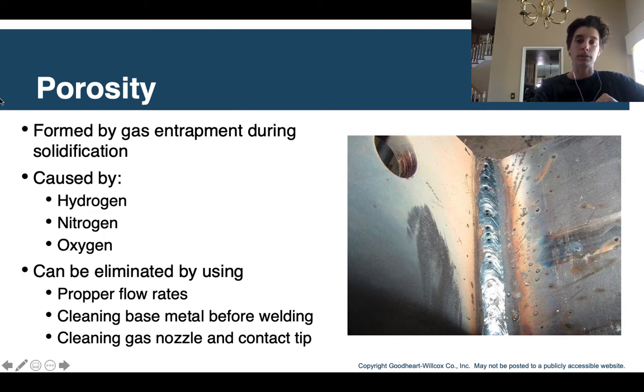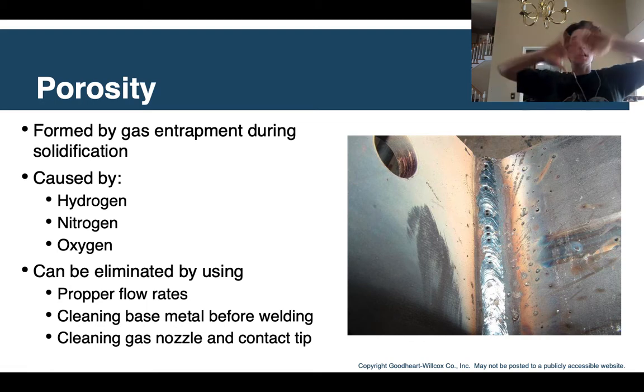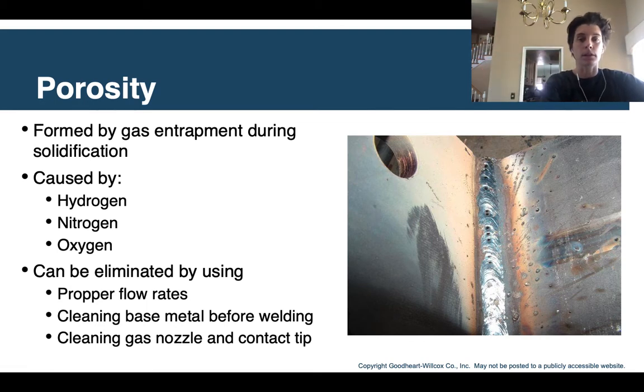cover in this lecture. So one of the main defects is going to be porosity. You've probably all encountered that in some form or another in your stick or oxyacetylene welding. For GMAW, for MIG welding, the porosity is often formed by gas entrapment during solidification. It can be caused by different gases. A lot of these are just in the air, in the atmosphere. It's not necessarily just the welding gas that you are using.